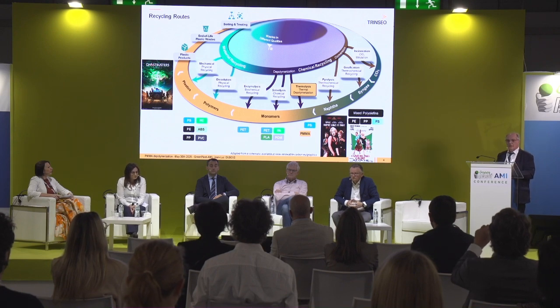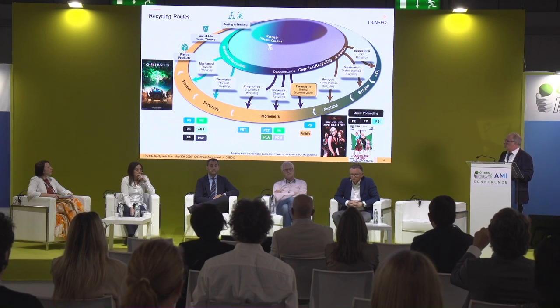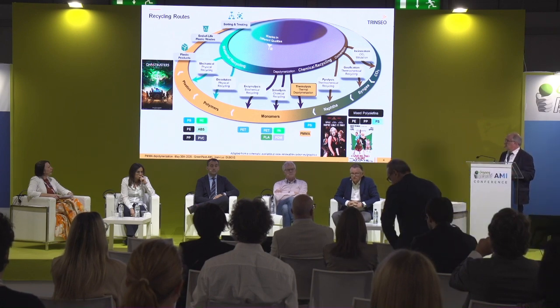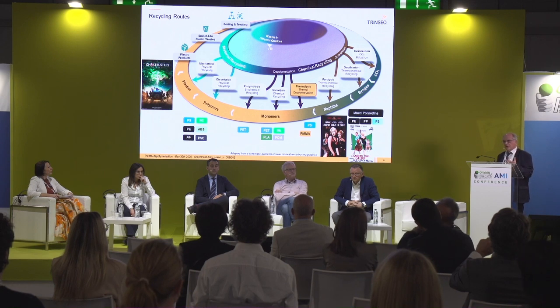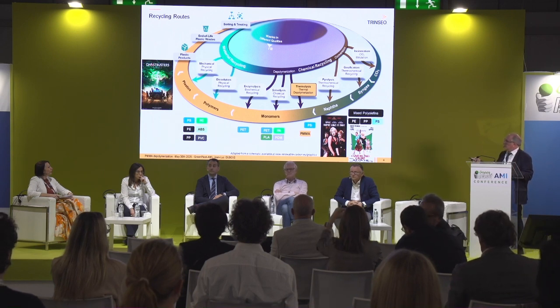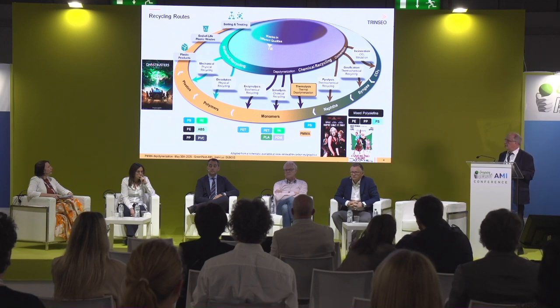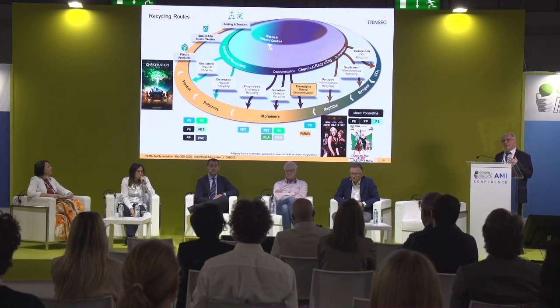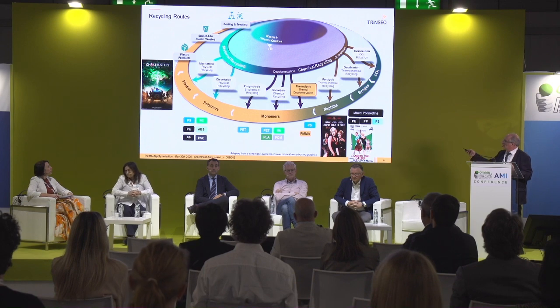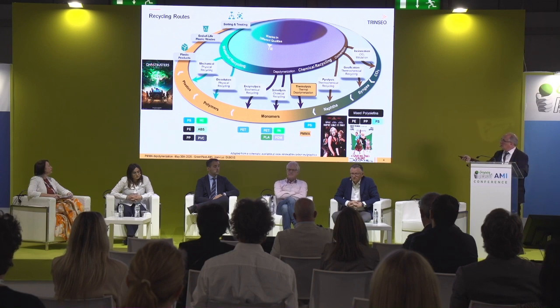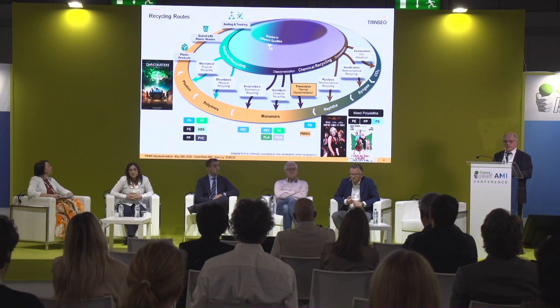Okay, the other type of technologies which are possible is solvolysis. It was mentioned before, which is appropriate for PET, for polyamide, for polyacetal, for PLA. In this case, there is a chemical reaction. The solvent is a reagent. There is a variation of that with enzyme and water. And then you have selective dissolution processes, which are more of a physical process. The main difference is that with those technologies, you change the molecular weight. You get monomer or oligomers. With selective dissolution, you don't change the molecular weight, like for mechanical recycling.